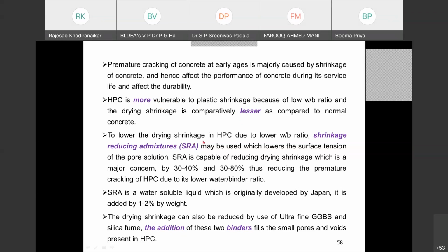The lower drying shrinkage in HPC is due to the low water binder ratio. Shrinkage reducing admixtures can also be used. They reduce the surface tension, and shrinkage reducing admixtures are capable of reducing drying shrinkage.